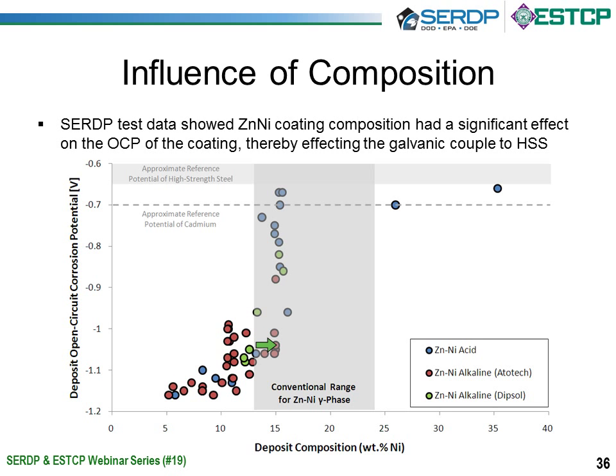And what we found was with using pulse plating, it was easier to maintain the composition in this range. And therefore, that was one of the reasons why we thought that the pulse plated material performed better than the DC material, because they were able to maintain the composition such that the open circuit potential of the material was close to that of steel.